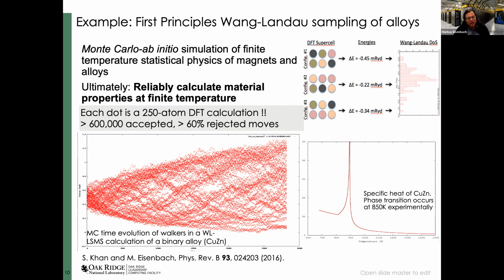Basically, as long as there are these very strong stripes visible, that also tells you that there is still some correlation in the walker, so the Monte Carlo is not converged yet. So ultimately it should spread out, and the structure should vanish mostly. I mean, there's always local fluctuations that could give you some pattern, but these whole stripes clearly tell you that there are still some